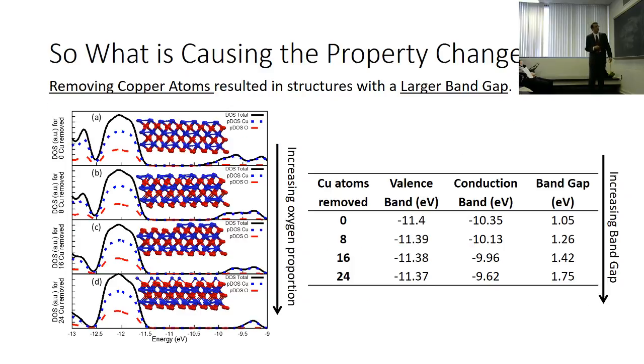We remove 0 copper atoms, 8 copper atoms, 16, increasing amounts of copper atoms. That leads to an increasing proportion of oxygen. And what we find is that the band gap does increase, quite drastically.